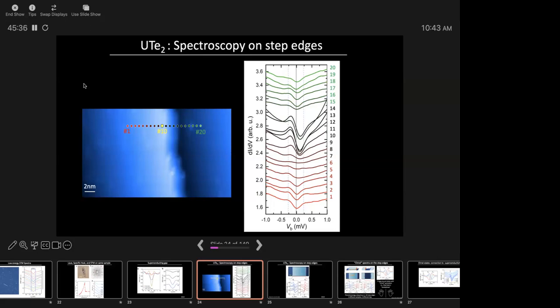So it's got this funny line shape. Look at this energy scale. The gap itself, I have to tell you, is 250 microvolts. It's tiny. And this funny thing lies inside the gap. So the peak is somewhere at 150 to 200 microvolts. And then correspondingly on the other side of the Fermi energy, 0 is the Fermi energy, you have a dip. So it's not nothing. On the other side of the Fermi energy, instead of a peak, you have a dip in the density of states at the same energy.